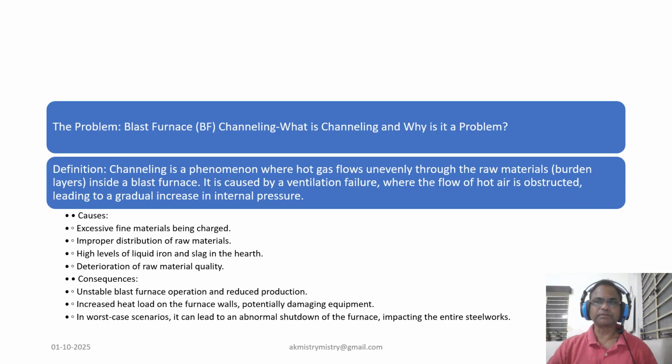Before going to that aspect, first of all, channeling is a phenomenon where hot gases flow unevenly through the raw material, that is the burden layer inside the blast furnace. It is caused by a ventilation failure where the flow of hot gases is obstructed, leading to a gradual increase in internal pressure.